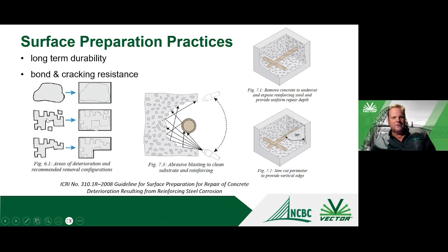And if you just chipped out the unsound concrete and did the repairs, all of these little reentrant corners are areas where you're going to have cracking. And so just from the geometry of the repair, going ahead and chipping out some sound concrete, and making your repairs as square or rectangular as possible, is going to help with the cracking resistance of the repair. The other thing to look at is the